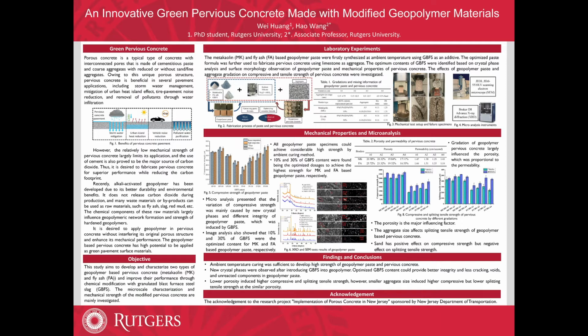As for the preparation, the metakaolin or the fly ash powder are first mixed with GBFS at different contents. After this mixing, the powder is then mixed with the alkaline solution, which is sodium silicate and sodium hydroxide. The cubical specimens with a dimension of 2 inches are prepared, and the microanalysis, including XRD and SEM, and the mechanical test, which is the compressive test, are applied on the geopolymer paste specimens to optimize the formula.